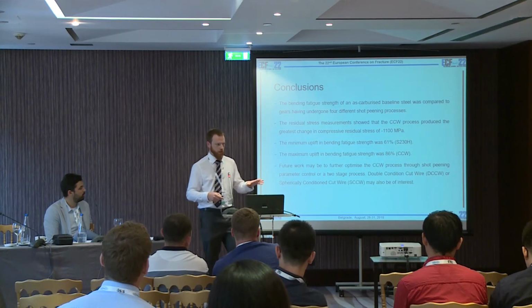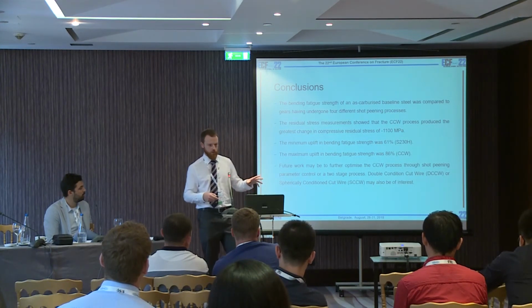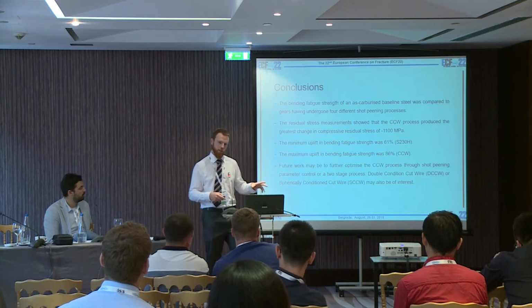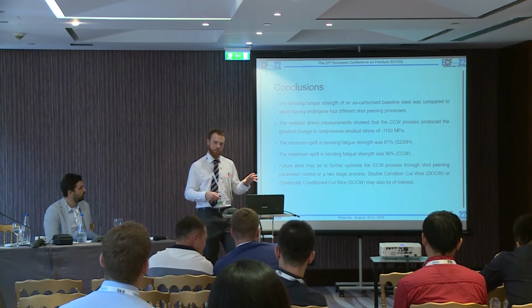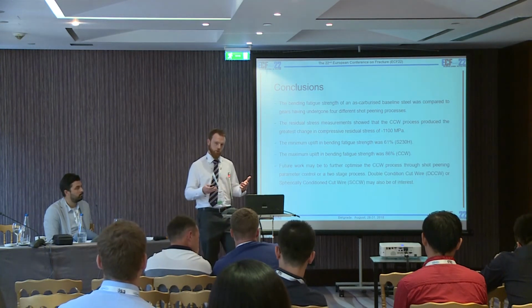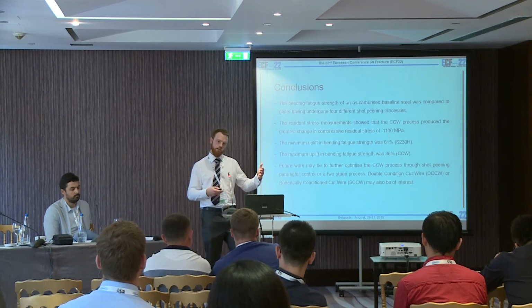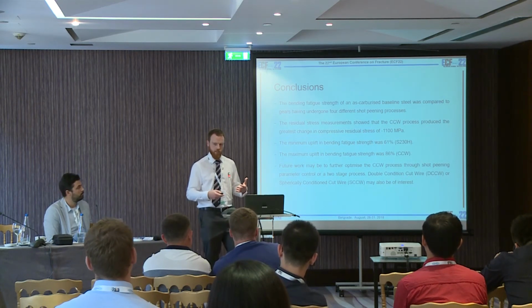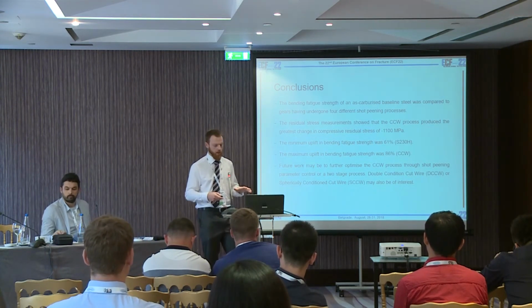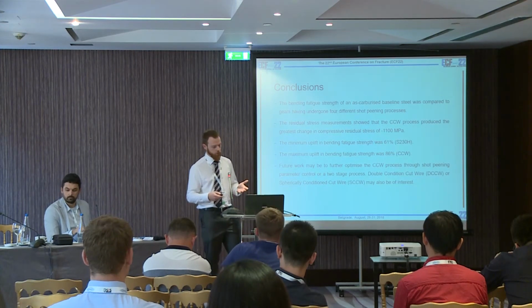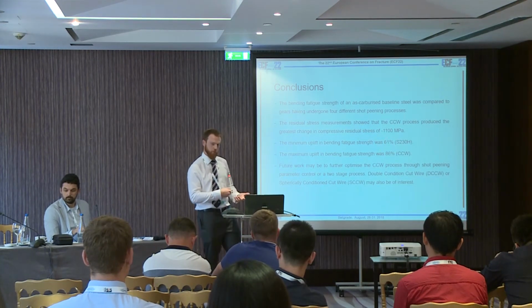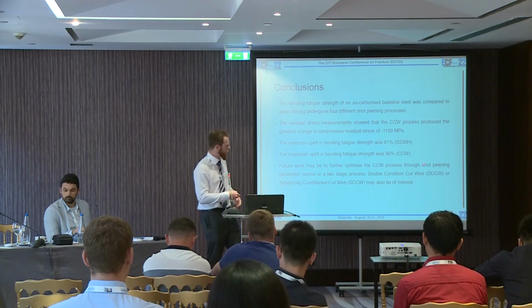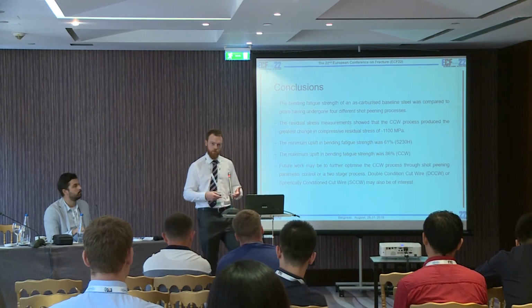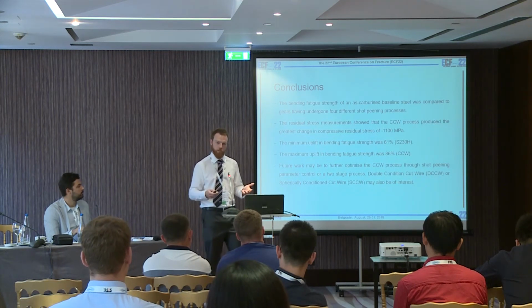Again, there is a bit of a side to that: ISO 6336 doesn't make it entirely clear what condition the material is. From our experience, it's actually as carburized and shot blasted. So shot blasting is used as a surface cleaning process. You do get some small compressive residual stress as well, but it does remove away that oxidized layer, and you generally see an increase of around 50% just from shot blasting. So if we use that as our baseline of 50%, then we see this 61 suddenly becomes 10%, which is what the standard suggests. However, the condition cut wire is still 36% above what we might expect for that, so it's very promising.